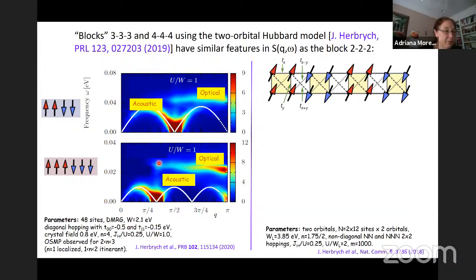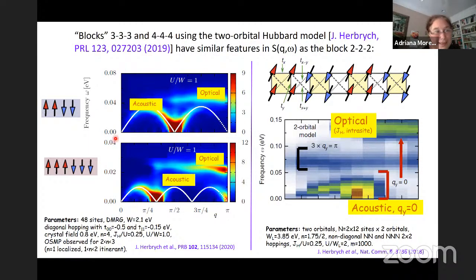We also did the calculations in a ladder to see that this wasn't something that only happened in the chains. In the ladder it's a much higher effort. We did it with a magnetic structure observed in the experiments for barium iron selenide, and we found exactly the same behavior - the acoustic mode and the optical mode for Qy equal to 0. For Qy equal to pi, because now this is a ladder, we found that there is a spectral weight, but much smaller. So most of these contributions seem to come from Qy equal to 0.